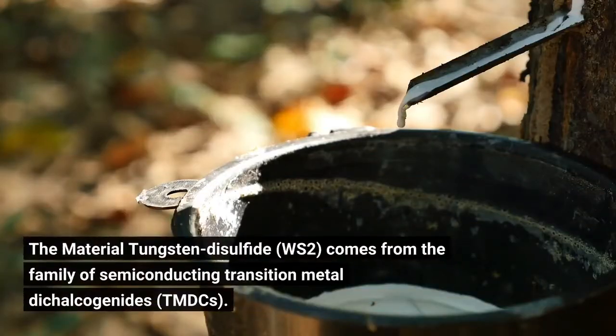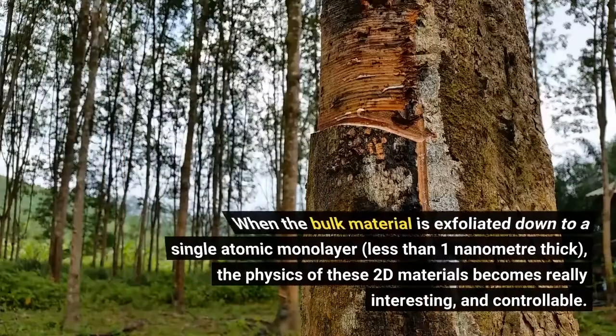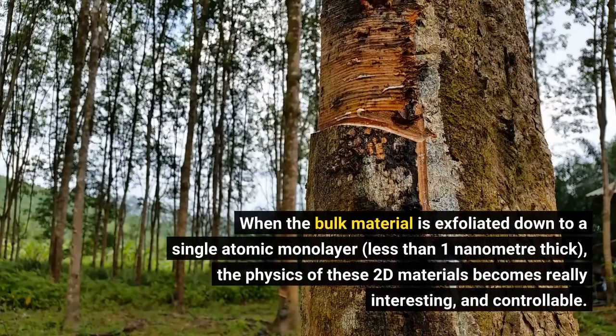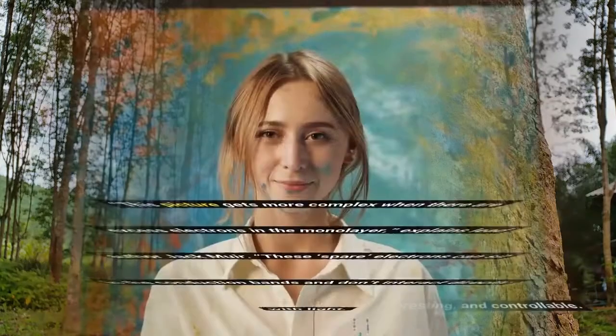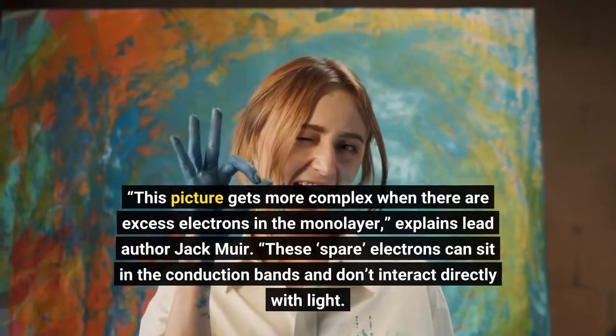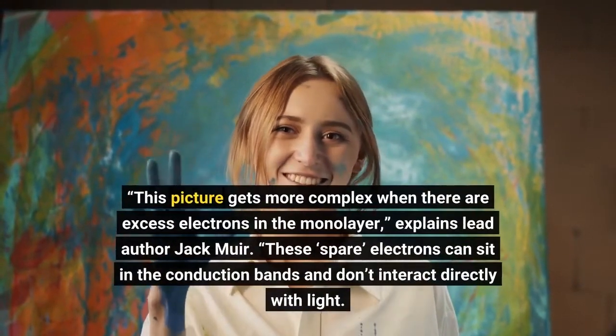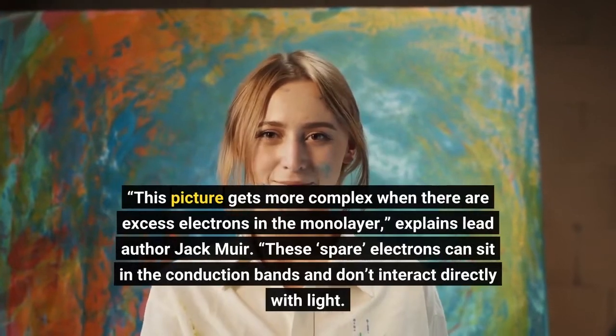The material tungsten disulfide, WS2, comes from the family of semiconducting transition metal dichalcogenides, TMDCs. When the bulk material is exfoliated down to a single atomic monolayer, less than 1 nanometer thick, the physics of these 2D materials becomes really interesting, and controllable. This picture gets more complex when there are excess electrons in the monolayer, explains lead author Jack Muir.